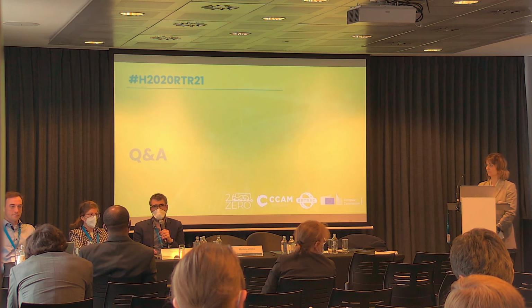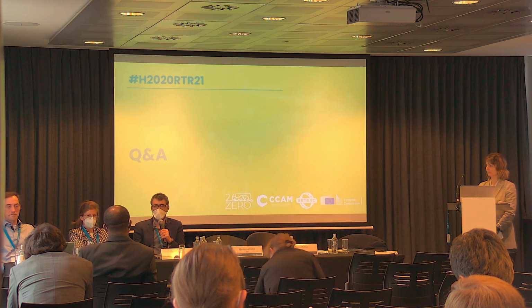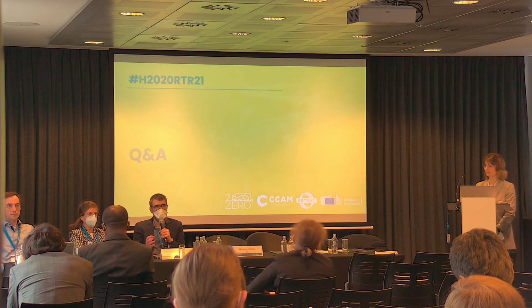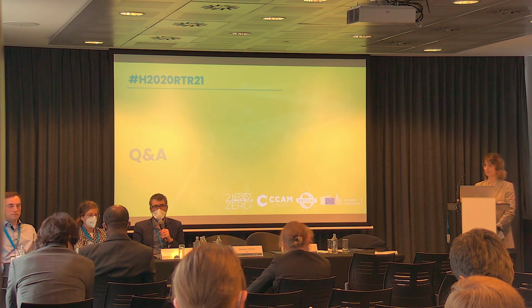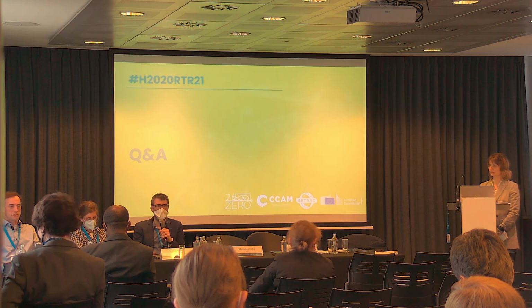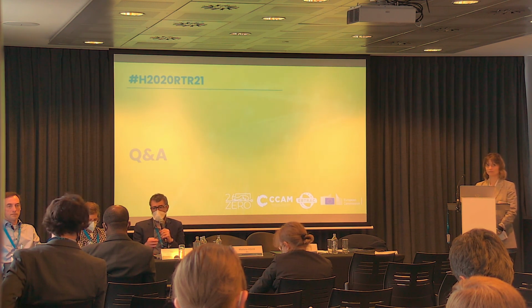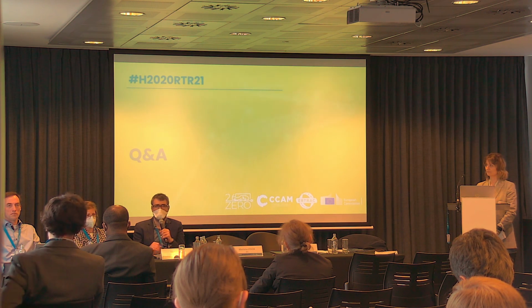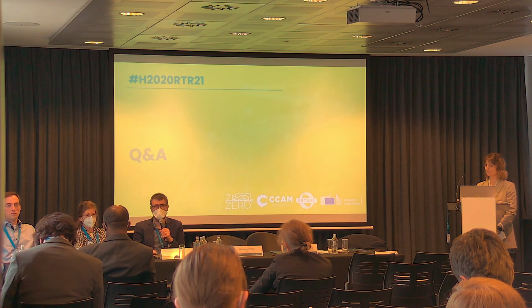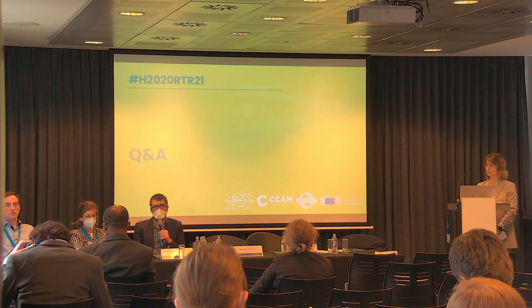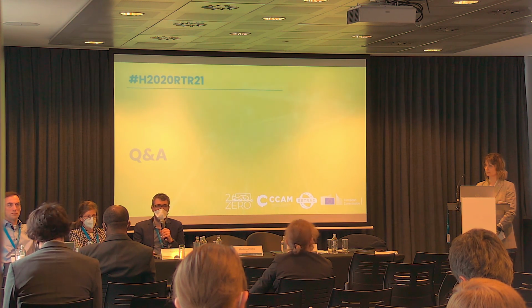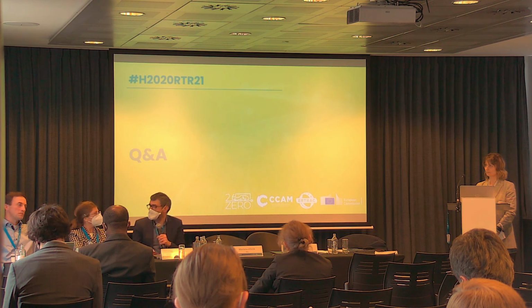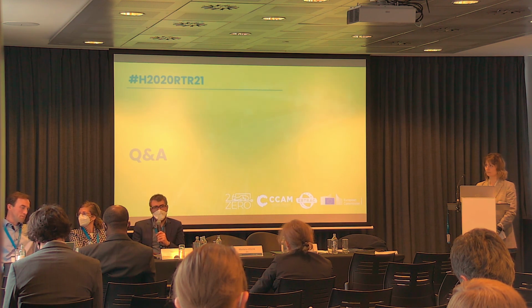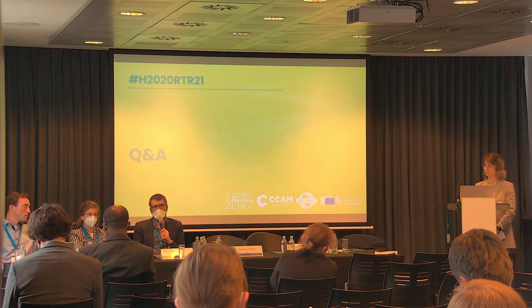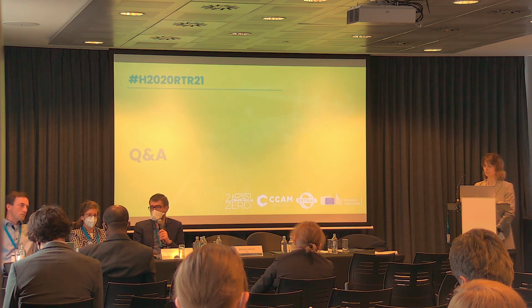We have dismantled coin cells that we have cycled in order to see the evolution of the silicon and the interface layers. We've seen some high SEI formation from some cycles that we can monitor. As I said, for the electrode level, we have some specific dilatometry tests to see the swelling of some electrodes without counter pressure. And finally, at the cell level, we have developed a dilatometer for the cells in order to evaluate the swelling, as was presented by AVL for this project, in order to see the impact of the pressure and the impact of the swelling, and correlate this with the model.